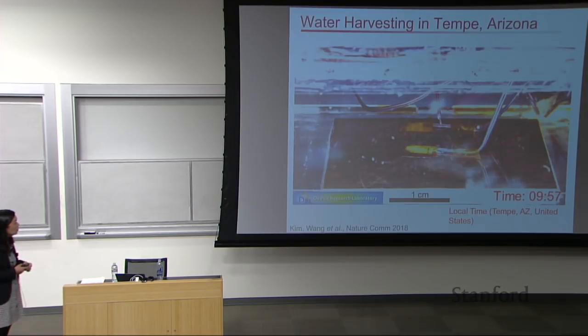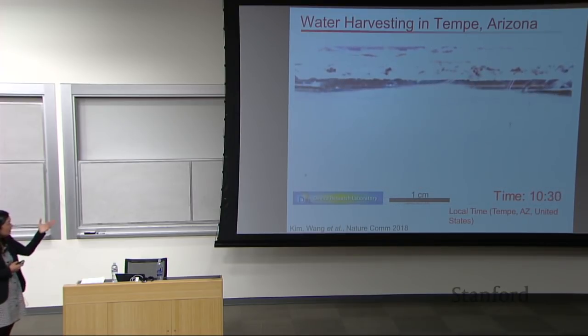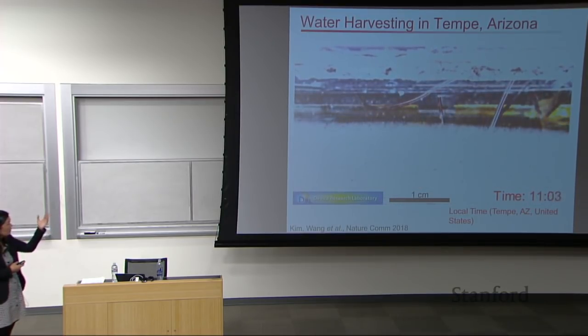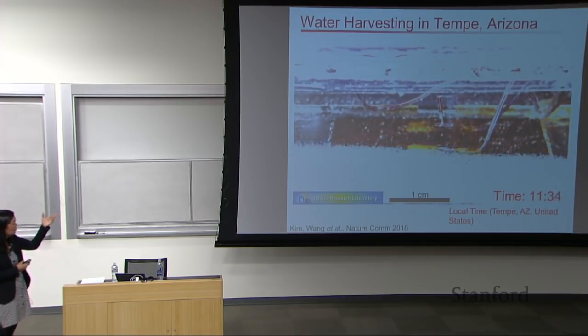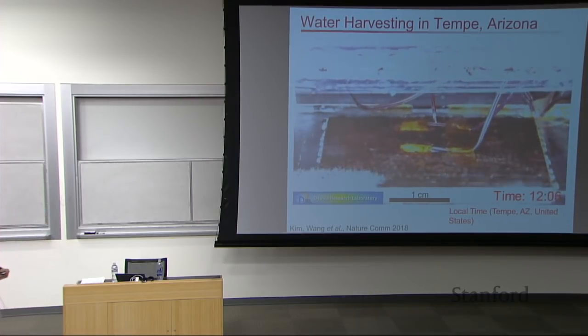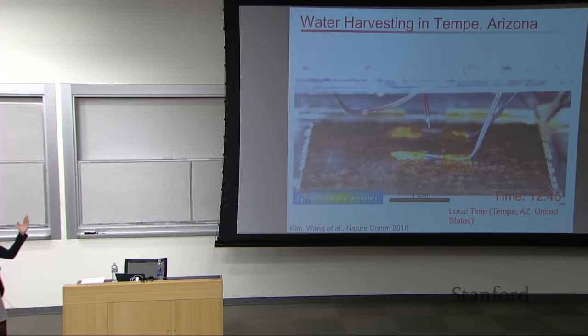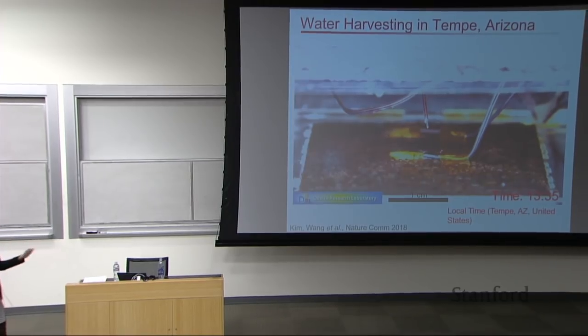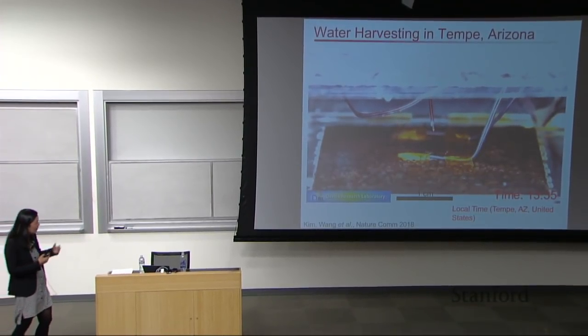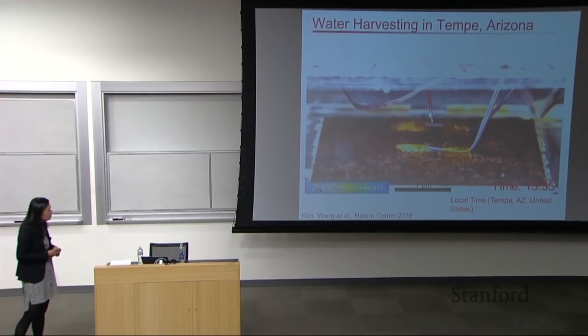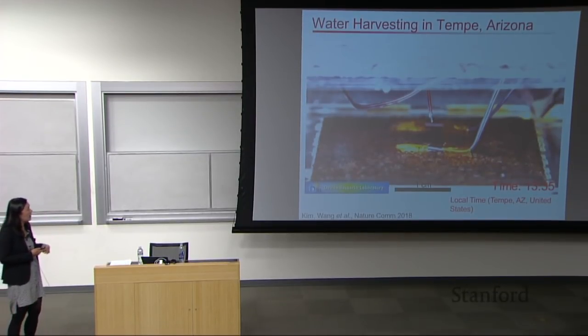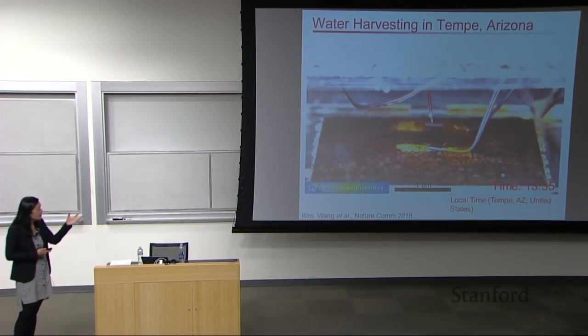Here is a video just showing you this process. You can see that immediately once you expose this device to sunlight, in the form of heat, you first see the whole viewport fog up, which suggests that it's condensing, right? But then as the system heats up, you start to see the fog disappear. And so in this case, we've been able to show that this device is operational.